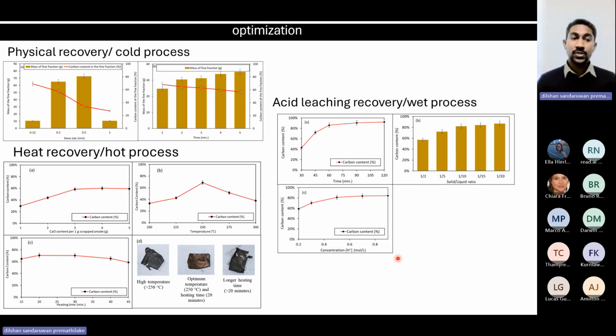For the sieve size also, I tried to optimize it using a variety of sieve sizes. And then I identified that 0.2 millimeter is the best condition for the extraction of graphite. In the acid leaching, or the wet process, I need to explain that I used aqua regia, the royal solution, to recover this graphite from the anode active material. I know that you may have lots of questions about why aqua regia, because I had the same question from several co-authors as well when I was doing this research.